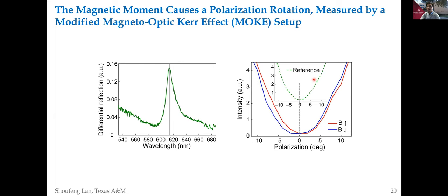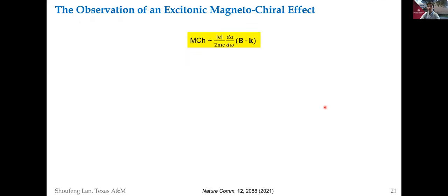For the reference sample, that is a monolayer WS2 on the silicon substrate, we see nothing because the minimum is at 0 degrees. But when we place this monolayer WS2 on the ferromagnetic substrate, for example, the red curve, the minimum, or the polarization rotation, will not be zero anymore; in this case, it's around 2 degrees. We further verify this phenomenon by switching the magnetic field from up to down. In this case, the rotation angle also flips. For example, for the blue curve, the polarization rotation angle is around minus 2 degrees. So we observe both the chirality and magneto-optical effects. And here comes our major result. At the beginning, we mentioned that the magnetochiral effect is proportional to the inner product between the magnetic field B and the wave vector k, as well as the derivative of the chirality, d alpha over d omega.